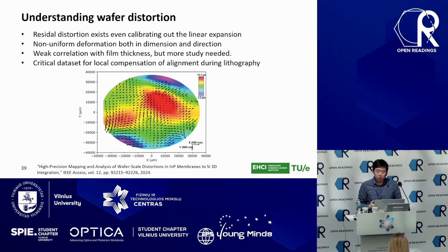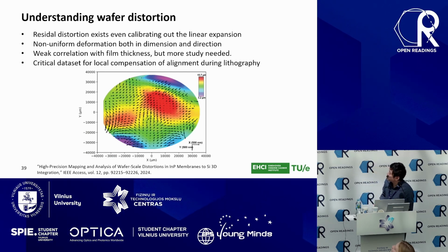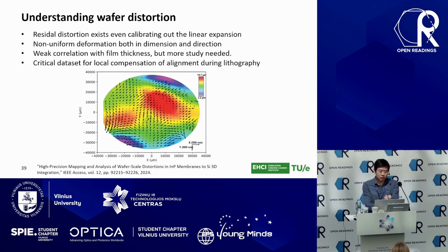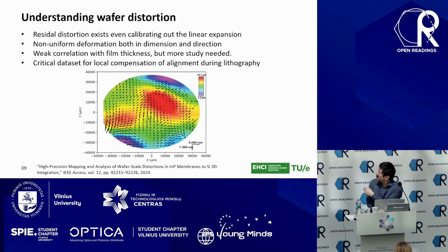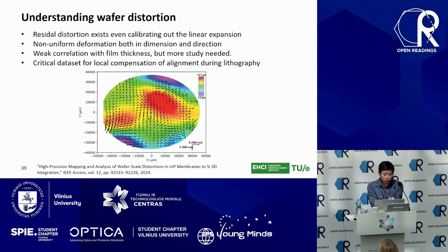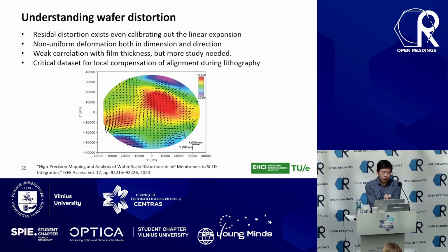And after calibrating out this linear expansion, you see there are nonlinear components remaining. So even after this linear compensation, we still have uncertainty of where each structure goes on this wafer. And this is ongoing research because we try to map these arrows, which show the nonlinear distortion, with the thickness of the layer stack, because there is some non-uniformity of the polymer involved. There seems to be some correlation between where the arrows point to and the thickness of the polymer.